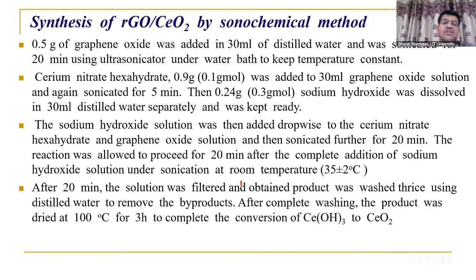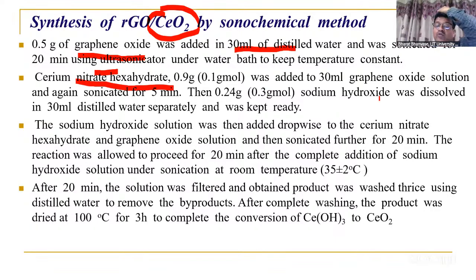Once we get graphene oxide, we have to load cerium oxide on that. For that, 0.5 gram of graphene oxide was added in 30 ml of distilled water, then sonicated for 20 minutes. Then cerium nitrate hexahydrate was added to the 30 ml graphene oxide solution and again sonicated.